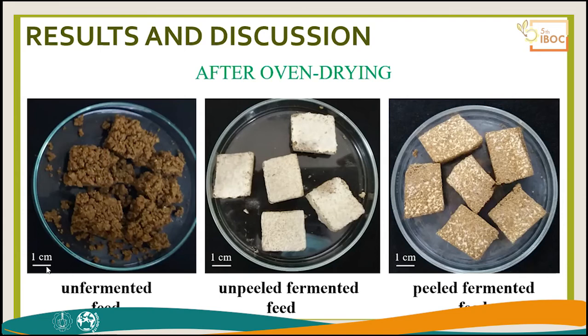The cubicle or block structure is preserved, indicating that the mycelium of the tempeh mold functions like joining the particles of the feed to make a single structure that does not easily break down. The one in the middle is the one with the mycelium surface intact, so without any peeling. And on the right is after the peeling, so the surface mycelium is completely removed.